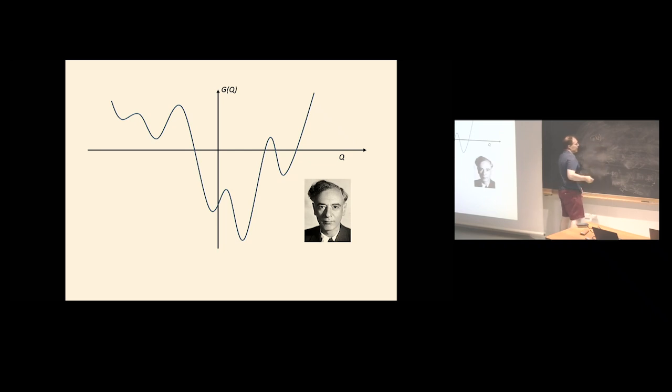So we have a prefactor in front of Q squared, which changes sign through the phase transition. How are we going to do that? Let's not just hold it in our heads, right? Instead, let's get it on paper. So now we're going to put a prefactor in front of Q squared, which has a constant positive factor we're going to call A. We're going to divide that by 2, and you'll see why later on.